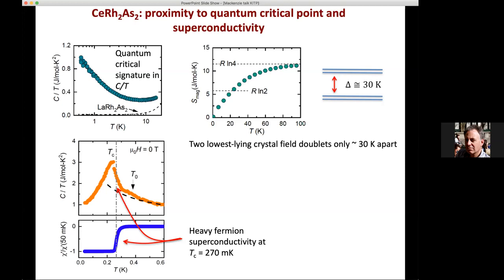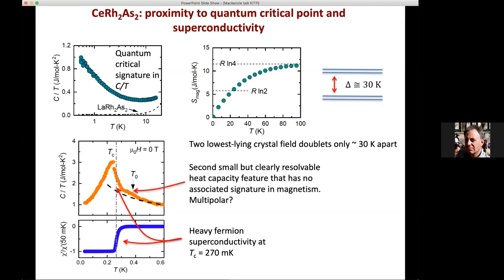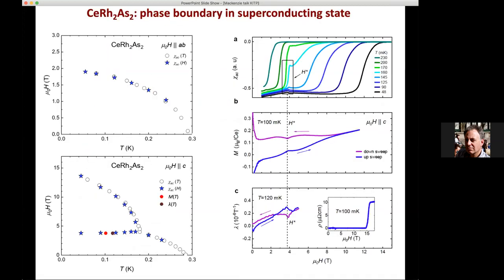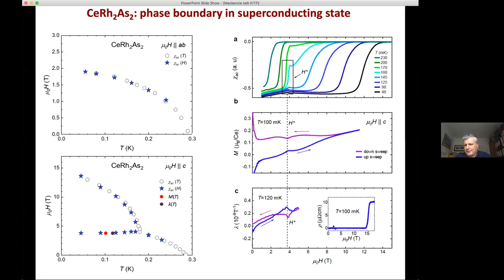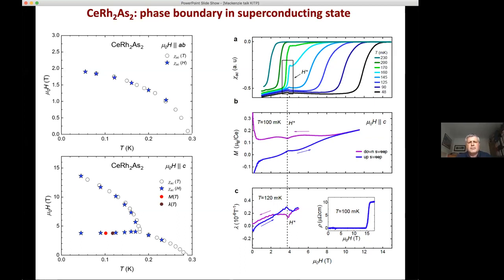A question from Jose Lorenzana: going back to the phase boundary between the two superconductors, you would expect that sitting right at the transition, the superfluid stiffness in the C-axis direction would become very soft exactly at the internal transition. So one might look for signatures of that — for example, resistivity reappearing at that point, or looking at the penetration depth. The response: we haven't looked at penetration depth, but we did check that there's no sign of going away from zero resistivity anywhere across that transition. The penetration depth is definitely an interesting point to pursue.